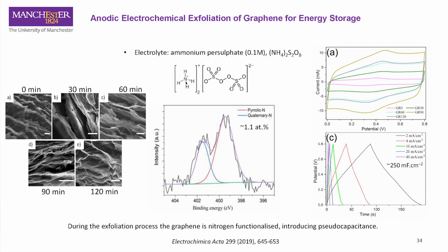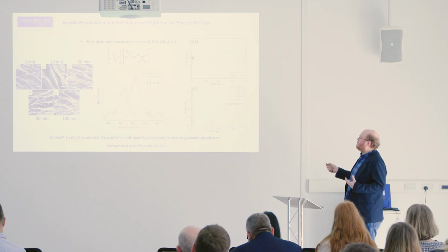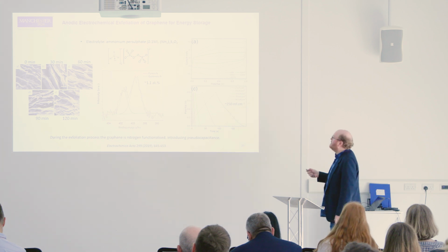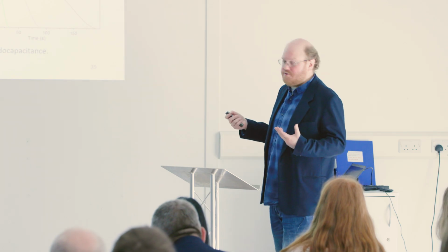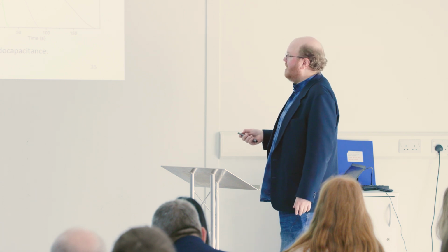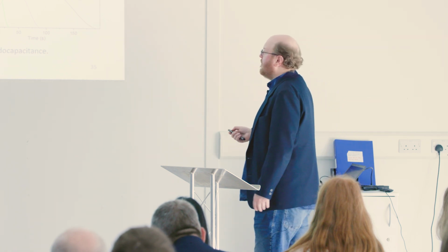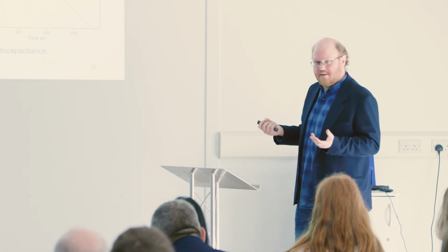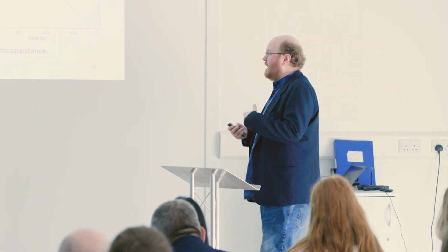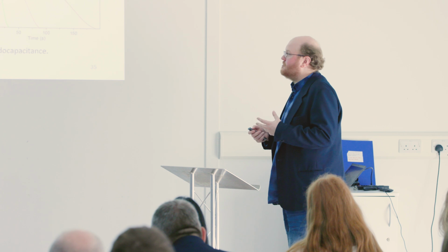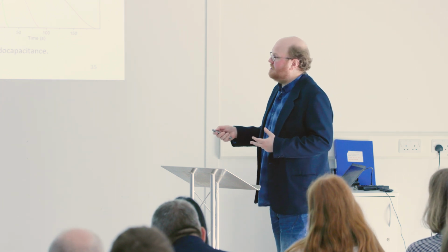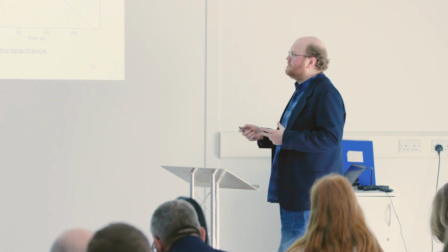But what we find is that gives us the pseudo-capacitance. Normally for capacitors, this would be a very nice square curve, which tells us the amount of energy we're getting out of it. These added peaks here are because we're introducing this nitrogen into the structure, and that gives us a higher capacitance. So we can get around 250 millifarads per square centimeter, which is pretty good. Normally, commercially, anything over about 100 or so is where you're interested in these devices. So as well as tuning the surface area, by having this surface functionality, by the way we produce it, we can get added benefits in the actual performance.